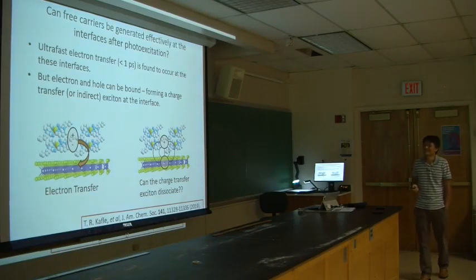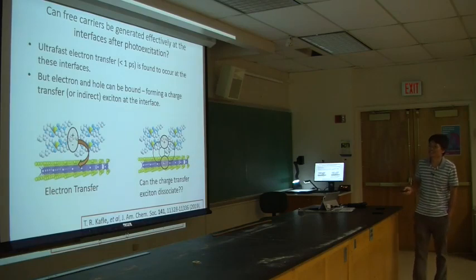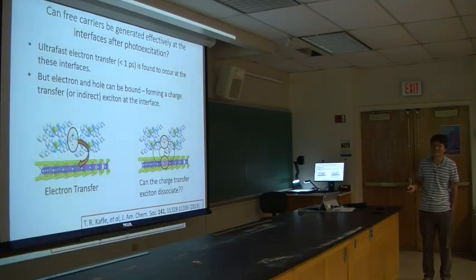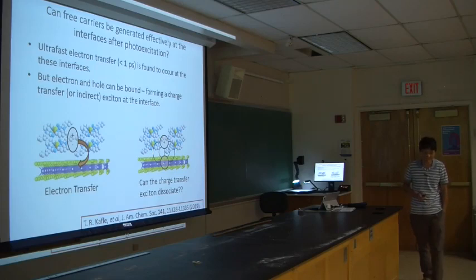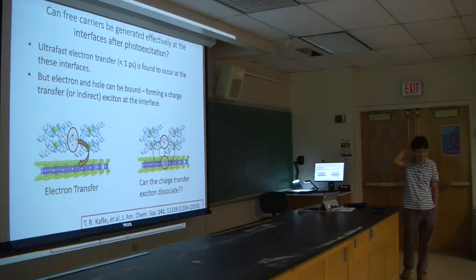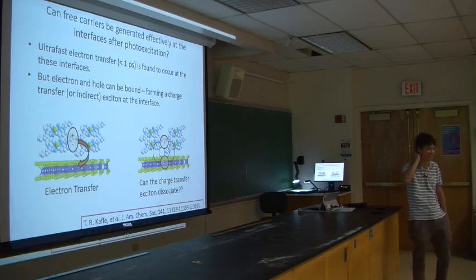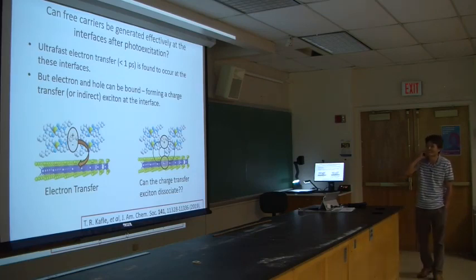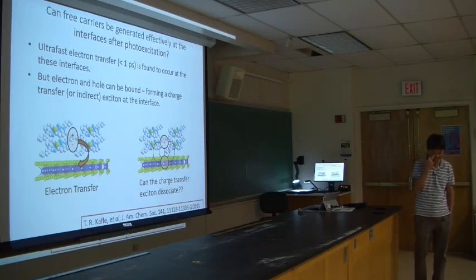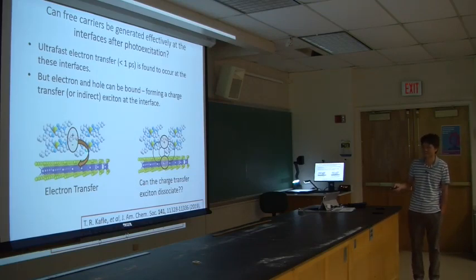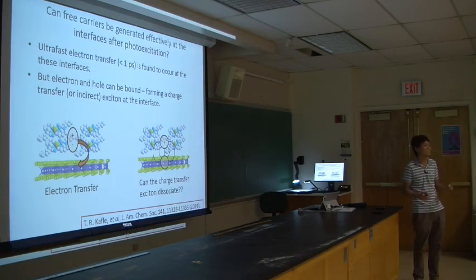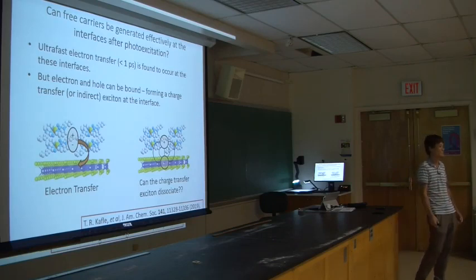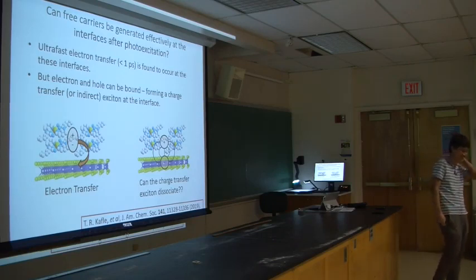And then the other thing that we are interested in is these organic 2D interfaces. Again, you excite an electron-hole pair in one of these materials, then you have electron transfer, and then generate these bound excitons. This material system is a little bit newer, in the sense that 2D materials are newer, so people didn't have much knowledge about how this occurs yet. But our focus here: if you look at the literature over the last few years, they often measure the initial charge transfer rate. Usually they see the charge transfer, then they think, okay, that interface is good. I can transfer electrons from one material to the other.